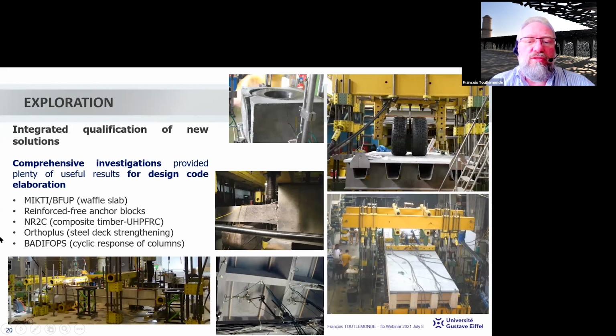We also developed finite element modeling with explicit accounting of fiber orientation, which is critical. This research was not only at the material scale but also in integral qualification of new solutions, such as reinforced free anchor blocks for post-tensioning, timber-UHPFRC composite solutions for short bridges, UHPFRC overlay to stiffen steel deck bridges, and testing of a column under both axial compression and a transversely applied seismic load.